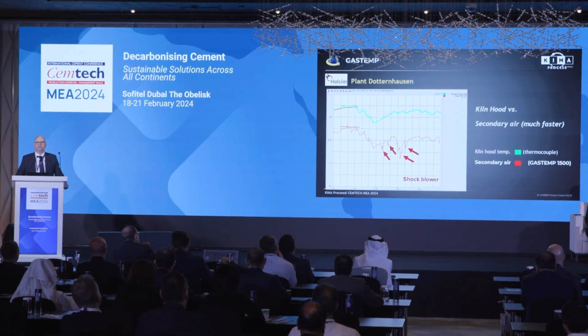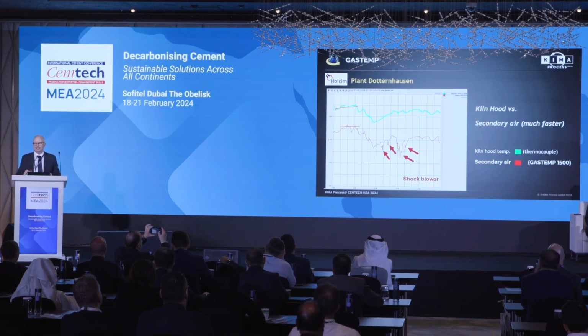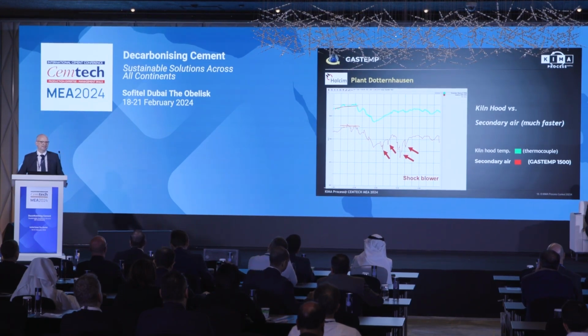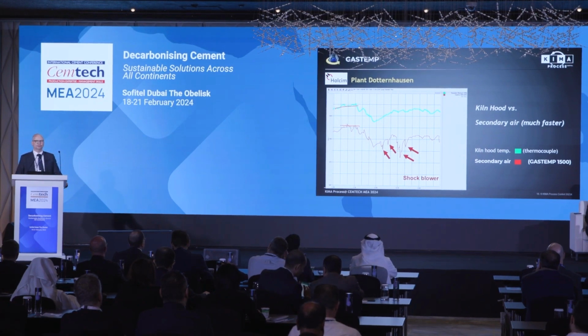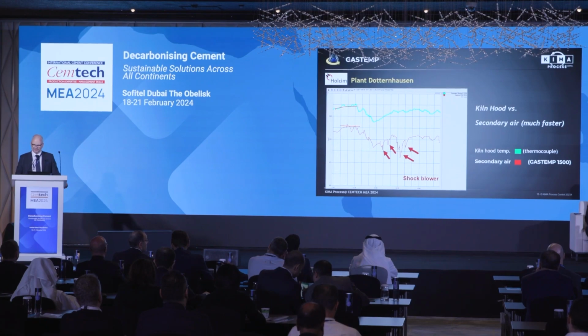And we are so fast that we even see when the shock blowers on the static grid of your clinker cooler are avoiding the snowman. We see boof, boof, that the temperature drops. Nothing to compensate, nothing to control, just to show you how fast this temperature measurement is.